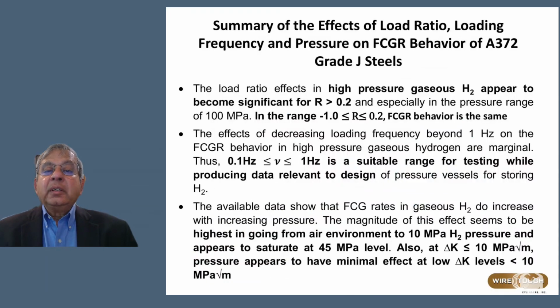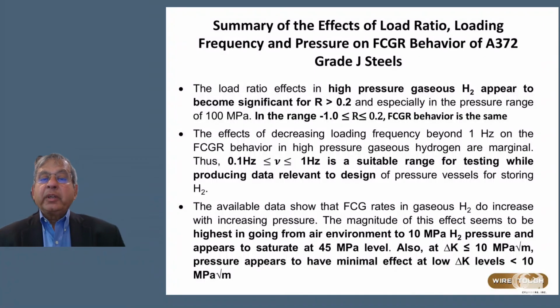So if we were to summarize the effects of load ratio, loading frequency, and pressure on the fatigue crack growth rate behavior of A372 Grade J steels, you would find that the load ratio effects in high pressure gaseous hydrogen appear to become significant for R above 0.2, and especially in the pressure range of 100 MPa. In the range of -1 to 0.2, FCGR behavior is almost the same. The effects of decreasing loading frequency beyond 1 Hz on the FCGR behavior in high pressure gaseous hydrogen are marginal. Thus, 0.1 Hz to 1 Hz is a suitable range for testing while producing data relevant to design of pressure vessels for storing hydrogen.